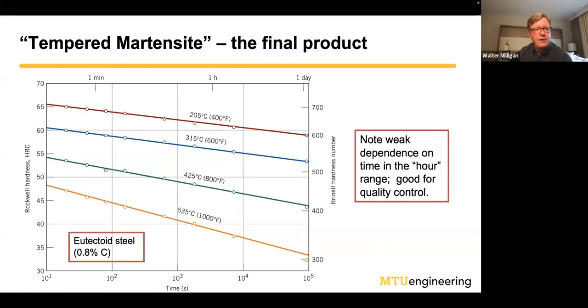And on the left-hand side, we have hardness, again in Rockwell C. And on the x-axis, we have time in the furnace. This is the same steel that I showed you that we did the quenching on. So this is piano wire. And so, for example, you can pick whatever temperature you want and then pick the time if you have the data for your steel. And so, for example, if I wanted to take this steel and temper it at 200 degrees C for about an hour, it should have a hardness of about Rockwell C62, which is harder than the hori-hori. And it's also a pretty good hardness for a plain carbon steel like this. As you increase the time or the temperature, the carbides grow more quickly, and so the hardness goes down. It's not always a bad thing.